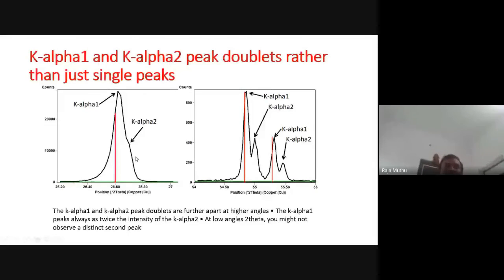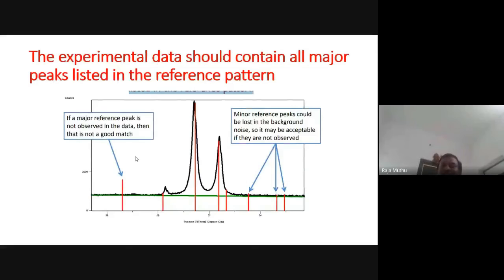The experimental data should contain all major peaks listed in the reference pattern. So the measured one should have all the reference peaks, right? If you see here, one peak is missed. This is a major peak. If the major peak is missed here, it cannot be accepted.